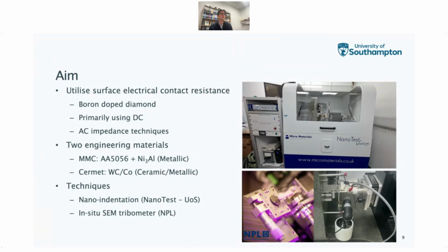So then the aim of the project was to see if we could do this through electrical contact resistance measurements. So we thought we might attempt to do this using a boron-doped diamond tip, and that's because diamond is often the material used for stylus instruments because of its hardness principally. But diamond does not conduct ordinarily, so you have to introduce some doping to change it into a semiconductive device. And boron is a good element to do that. And then we deployed it primarily in a direct current mode using the platforms there. And then later on, as I mentioned, using some AC impedance techniques as well.